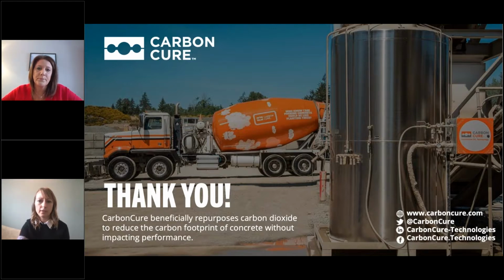I had a question to repeat the cement percent savings in the usage of CO2 and also the ASTM compliance number. So ASTM C494 type S. And then Shannon, if you can recap on the cement savings percentage. Yeah, so that varies. I mentioned a couple different percentages. When we're talking about an improvement to compressive strength, I said we've seen up to a 10% improvement. And when we're talking about reduction of cement, it is going to vary on your regular mix performance, plant variability, and mix design, but on average, it's between 5 and 7% of a cement reduction, cementitious reduction that you're able to take on your mixes.